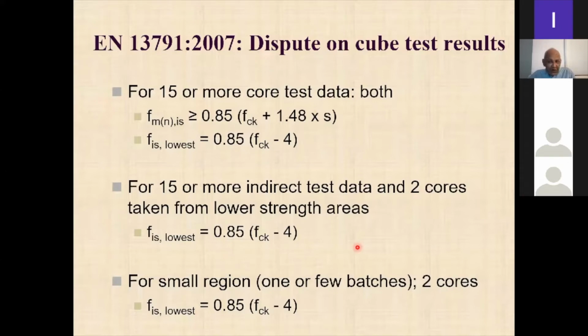Then if you have already made some notes on the site as to where that concrete went, you can take 2 cores from that, right? And then you are not allowed to use the mean strength. You take the lowest strength, which must be greater than 0.85 times whatever grade you are supposed to achieve in the cubes. The grade you are supposed to achieve is 25, 0.85 times 21. So it's a fairly small value, right?